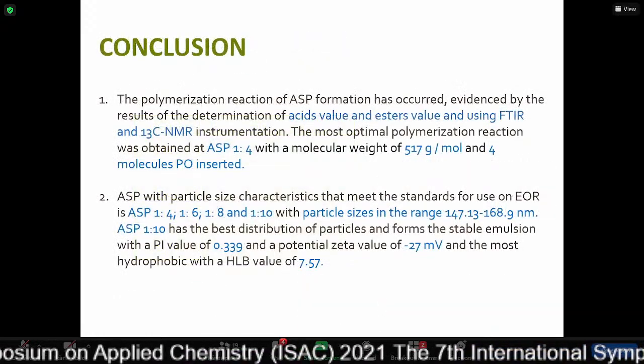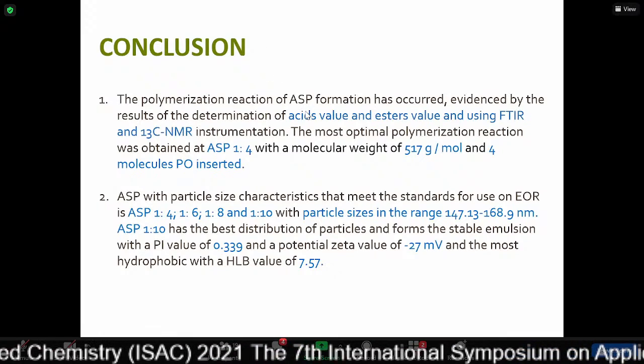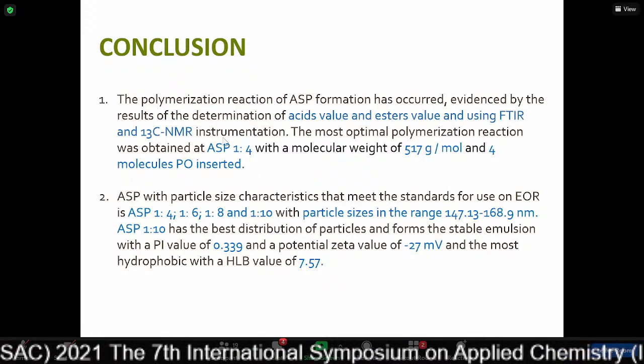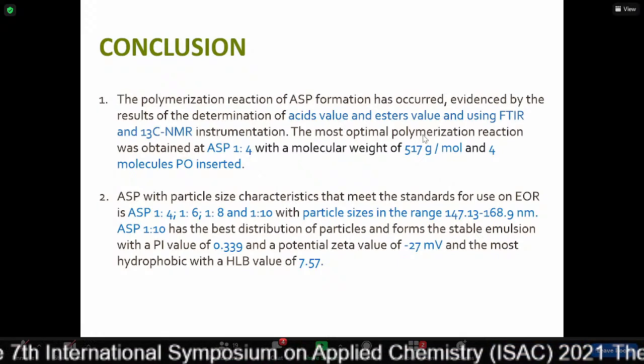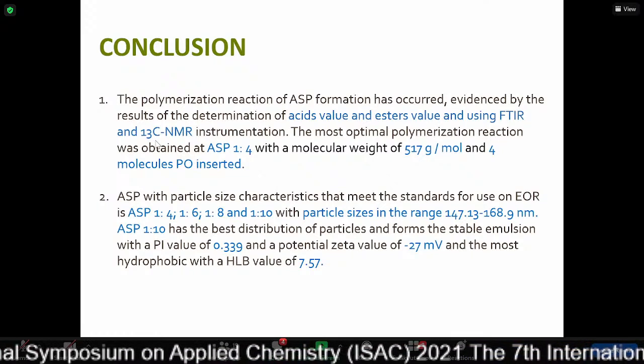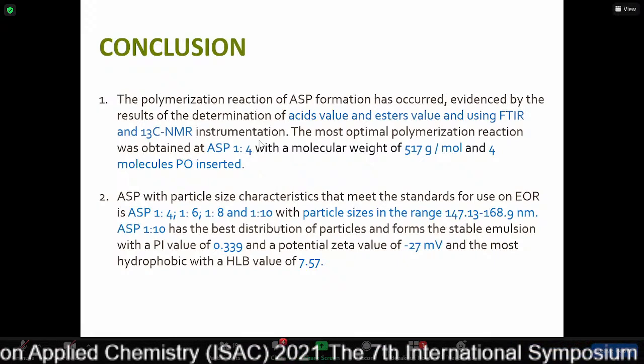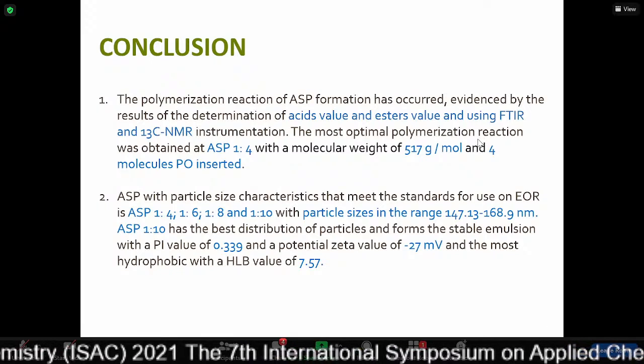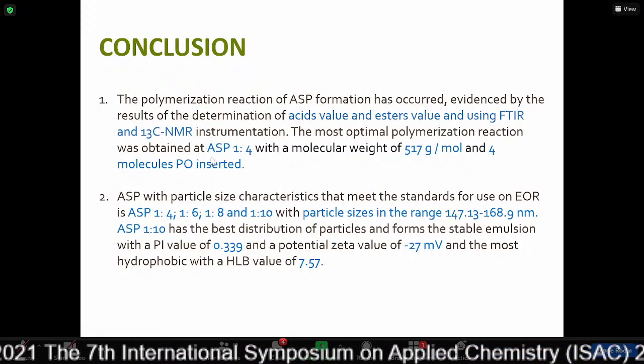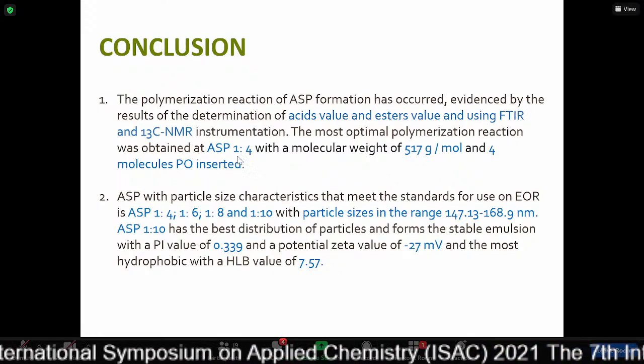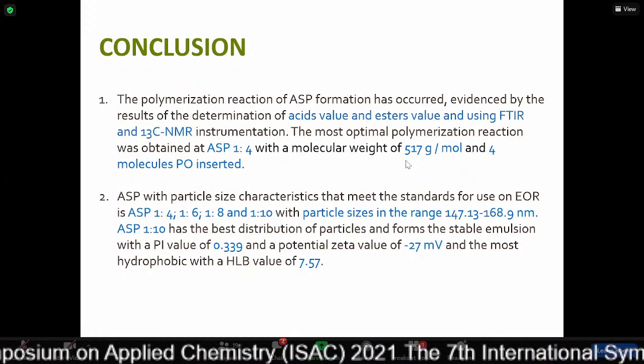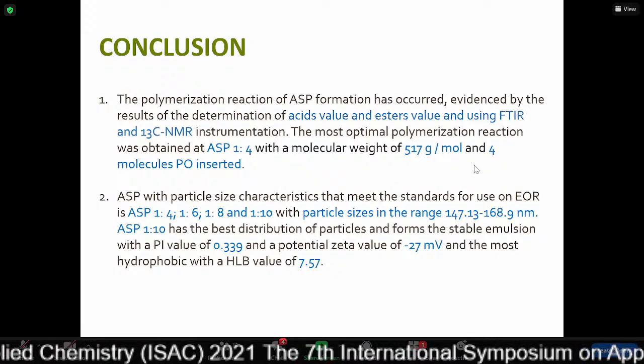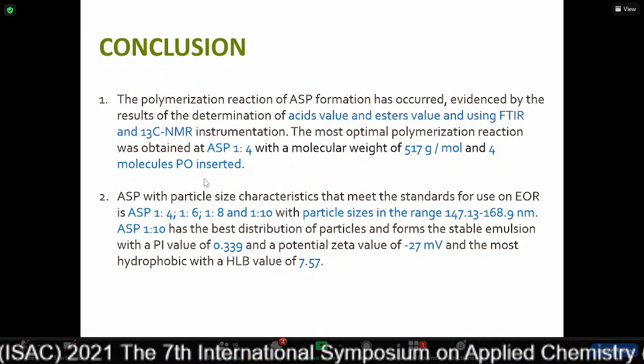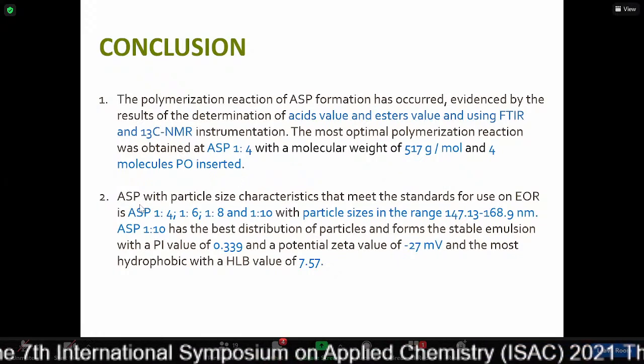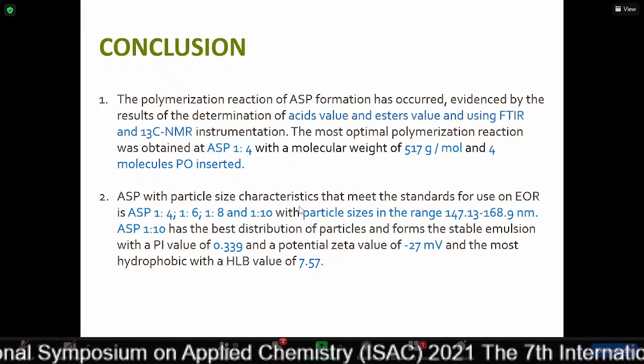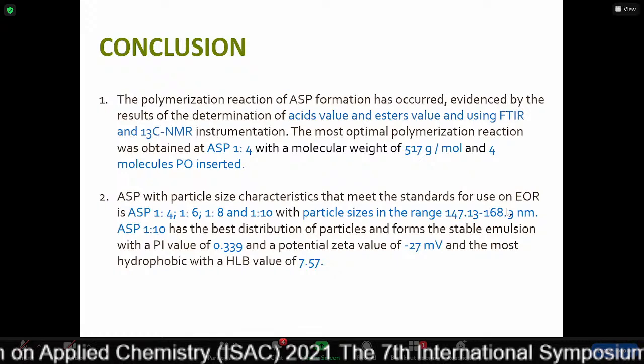So for the conclusion, the polymerization reaction of stearic acid propoxylation has occurred, evidenced by the determination of acid value and ester value, and also by the data from the FTIR and 13C NMR instrumentation. The most optimal polymerization reaction was obtained when the ratio of stearic acid to propylene oxide is 1:4, with a molecular weight of 517 grams per mole, and 4 molecules of propylene oxide inserted into this polymeric surfactant.